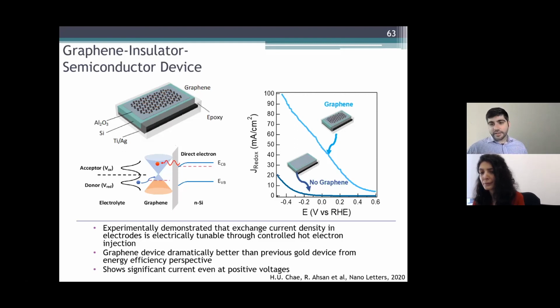and we can model it, but the reality is that you have to consider the fact that the tunneling models you use tend to underestimate the effect of your non-ideal tunneling rates, like trap-assisted tunneling and whatnot, which really reduces the amount of voltage that gets dropped across your oxide, which really reduces how hot your electrons are when they're injected into this material. Sorry for the convoluted answer to your question, but there is no simple answer as far as I know right now, anyway.